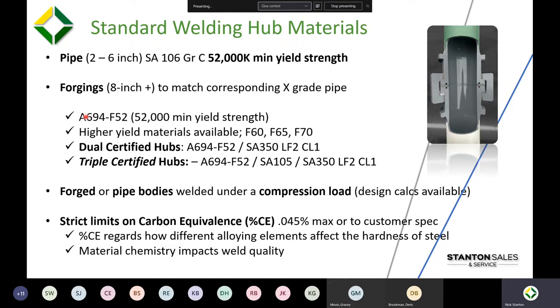We dual certify, at minimum, we dual certify our weld hubs with any product. Closures, insulated joints, anchor flanges. So we use high yield material and we combine it with SA grade material, typically SA350 LF2 class 1, the low impact, low temperature alloy. Or we triple certify the weld hub with the addition of SA105 for its hardness to help ensure a good quality weld.